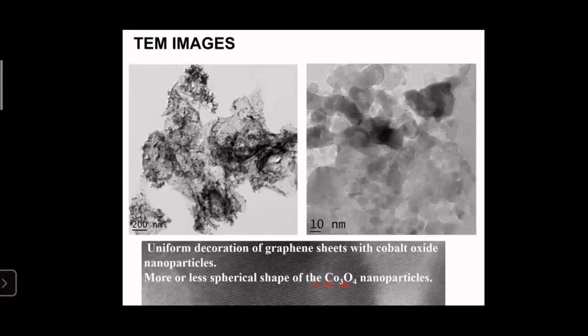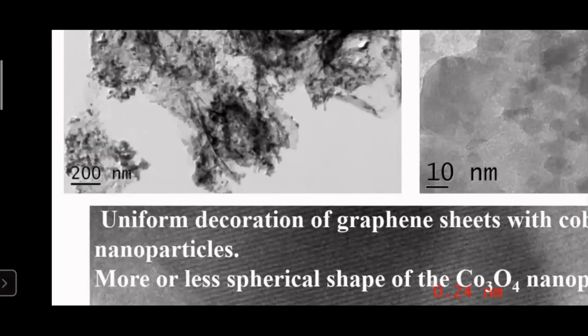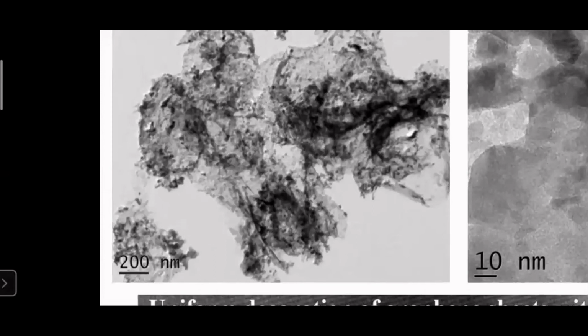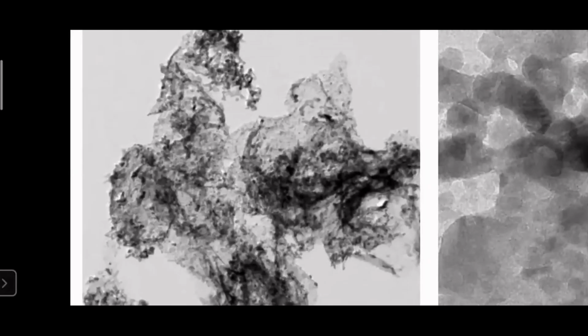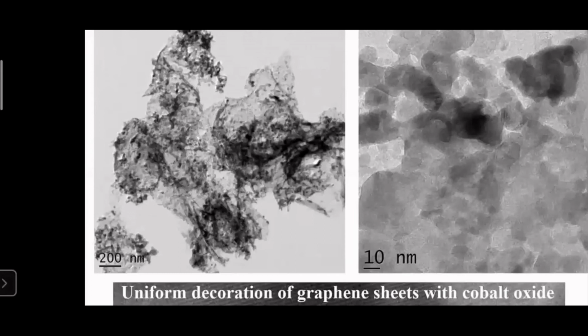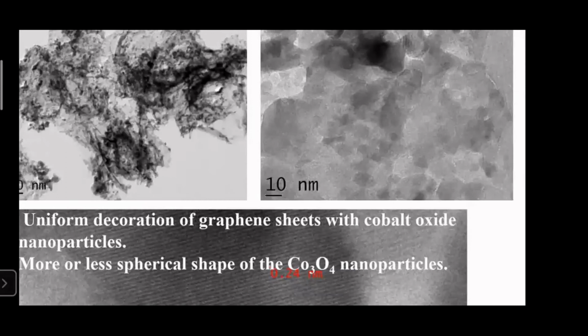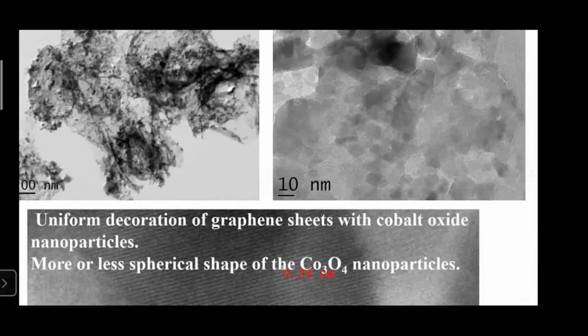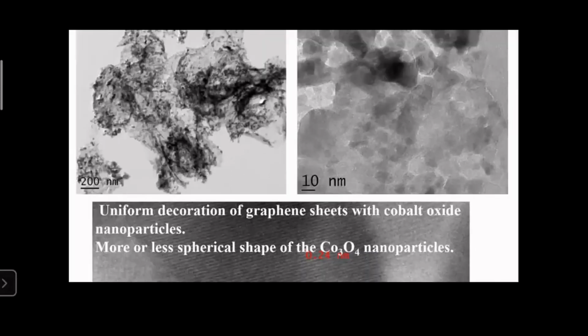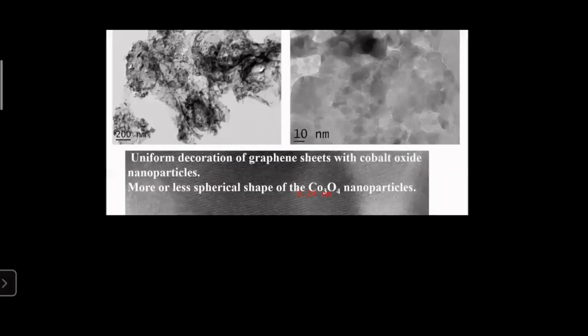Then we check the TEM images of the composite so as to confirm the formation of a stable nanocomposite. If the composite is not stable, we can see particles outside the sheets. But here, all the cobalt oxide particles are well-defined and well-dispersed on the graphene sheets. The particle size is found to be in the range of 5 to 15 nanometer, and the material is almost spherical in shape. The lattice fringes of Co3O4 are also visible from the TEM images.